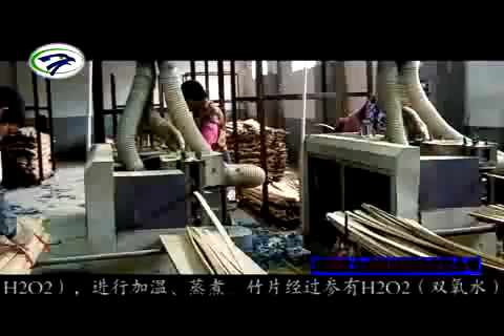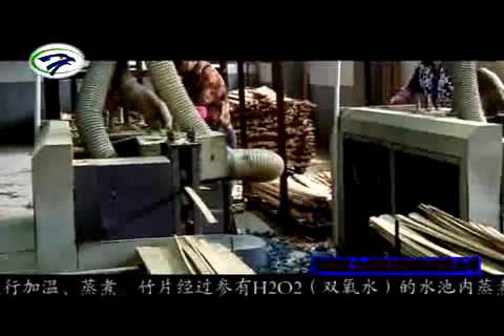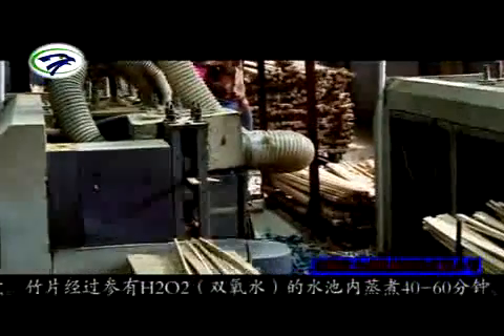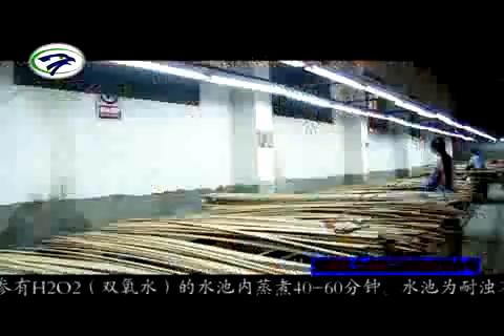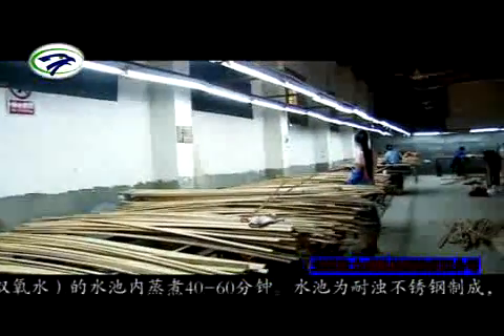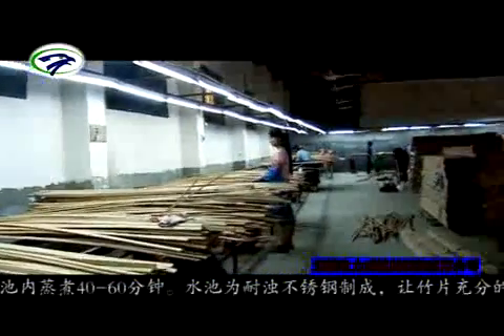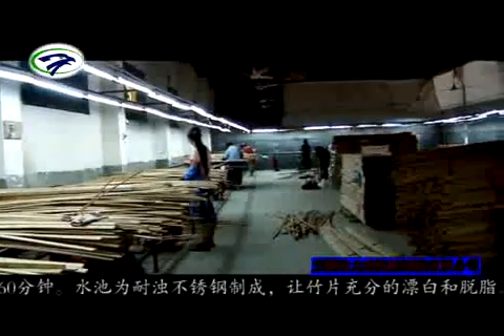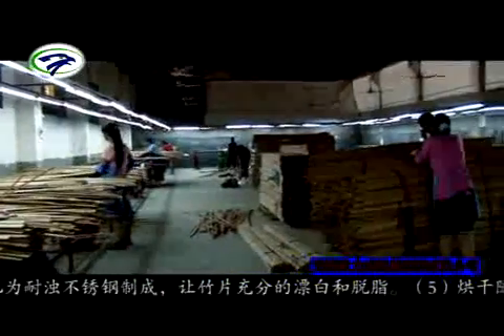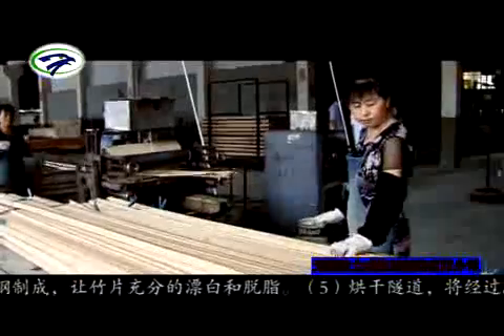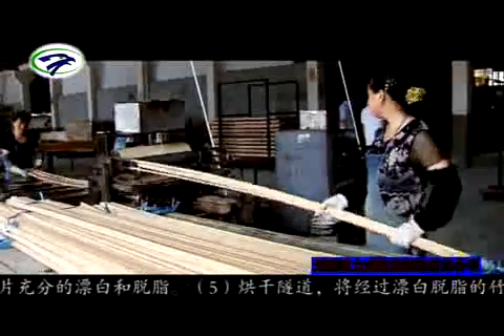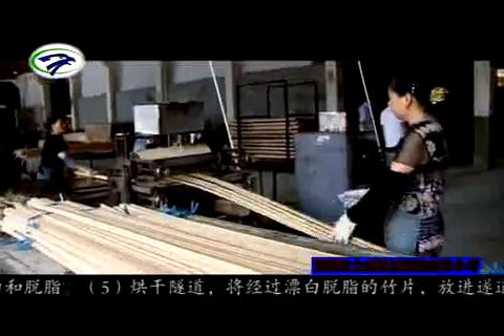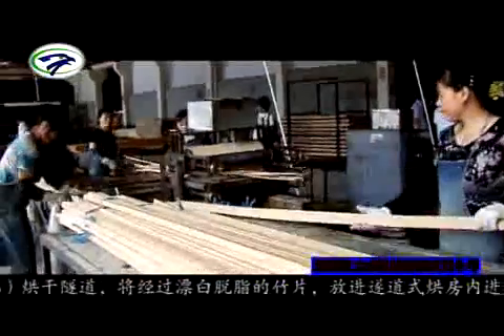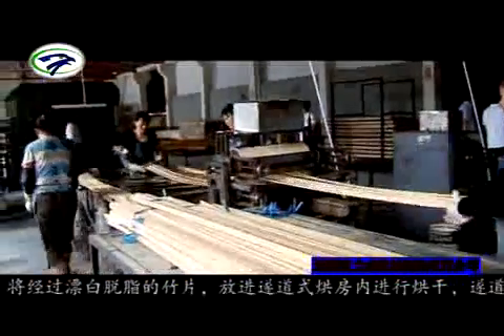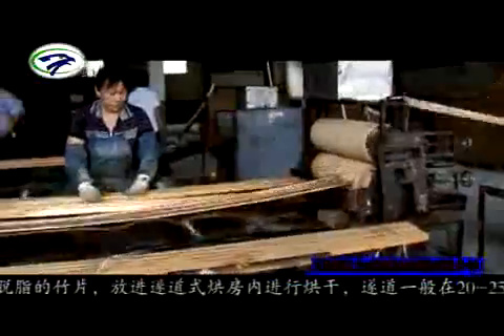4. Bleaching and degreasing. The rough planing bamboo strips must go through the bleaching agent, H2O2, for heating and stewing. The bamboo strips should be in the pool of hydrogen peroxide for 40 to 60 minutes stewing. The pool is made from corrosion-resistant stainless steel to make the bamboo strips bleach and degrease fully.